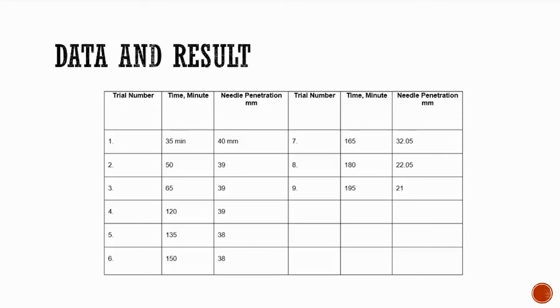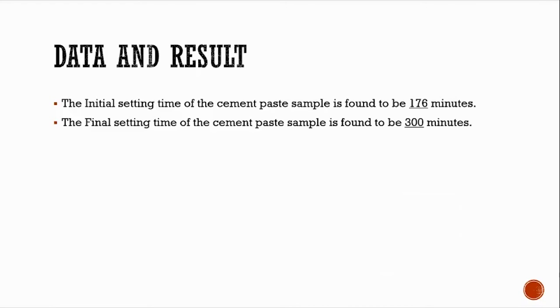Trial number 7, time is 165 minutes, and needle penetration is 32.05. Trial number 8, time is 180, needle penetration is 22.05, and trial number 9 is time 195, needle penetration is 21. For the result, the initial setting time of the cement paste sample is found to be 176 minutes, and the final setting time of the cement paste sample is found to be 300 minutes.